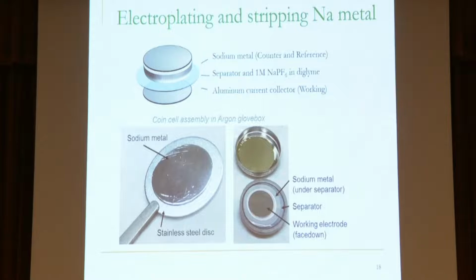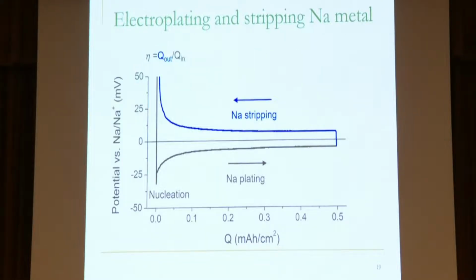And so basically our sodium looks something like this, right? And we put that with a separator and another electrode. We seal it inside this little coin, and then we go ahead and test it. Now, what are we testing? So the most common way that we test batteries is something that we call galvanostatic cycling. All that means is that we apply a constant current to the battery as we're cycling. We end up getting this process where sodium nucleates on the other electrode, and then it just continuously grows, right?